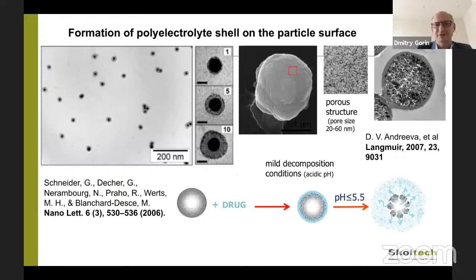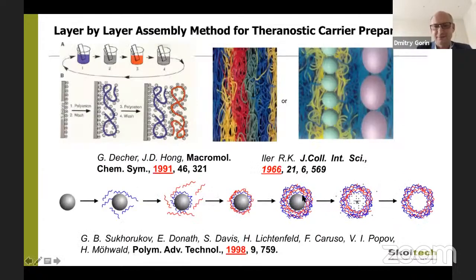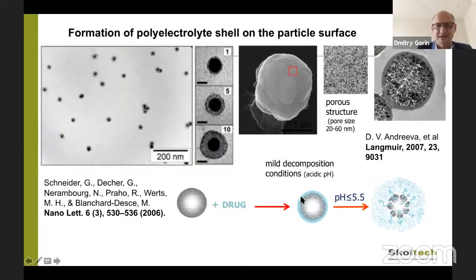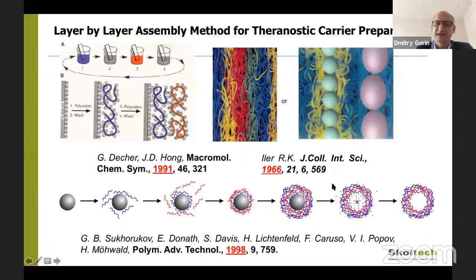In this case, we can use as a core, for example, vaterite particles, and we can dissolve these particles with some organic substance, EDTA. This substance is used for blood conservation, for example. The idea is that this organic molecule can form a complex with calcium ions, and then we can dissolve this core. It works because our shell is a polymer shell, and it is penetrable to the calcium ions.